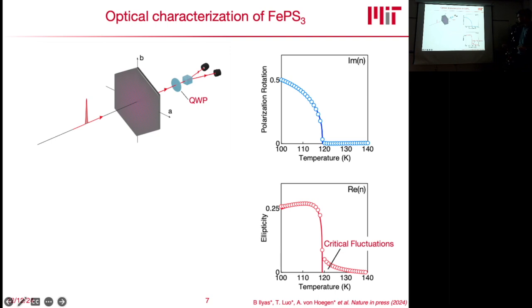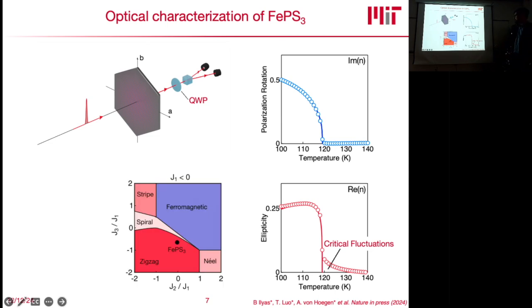And also what we see here is that in the ellipticity, for some specific reason, we see so-called critical fluctuations. So there is already an ellipticity signal above the critical temperature, which can be explained by the fact that this material is predicted to be very close to a ferromagnetic state, so that your system is already kind of fluctuating and you pick up these fluctuations in this ferromagnetic state with this type of measurement. And so this is ingredient number 2 that we need. We can optically probe this material in its magnetic state.